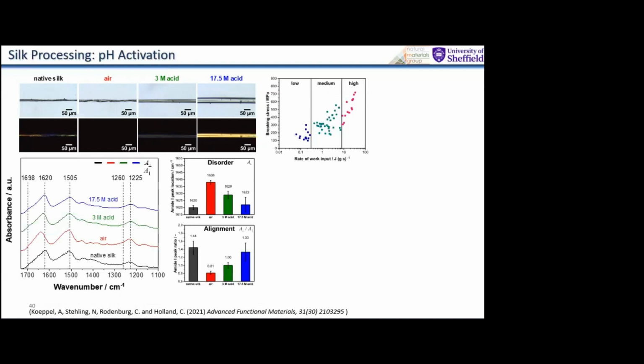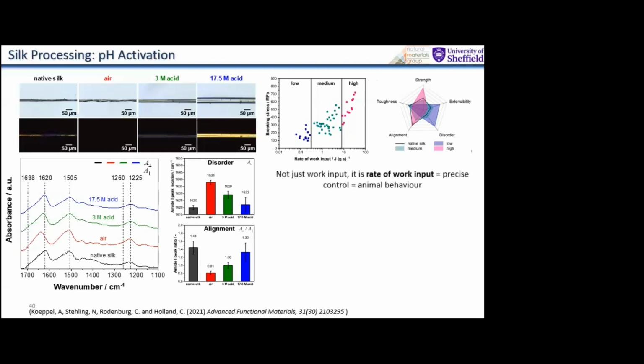Not only that, we were able to compare the amount of work put into forming that fibre. And what we found is that the mechanical properties of our ex vivo spun, our artificially spun natural silks, depend on the amount of work input that you put into it. So if the spider's working really hard and pulling it out and sweating, it's making a good silk. And we can start to relate the rate of work input to fiber properties, which is super exciting because that's animal behavior. Animals change their spinning behavior to modify the properties of the fibers that come out of their body. And that depends on how silk self-assembles.